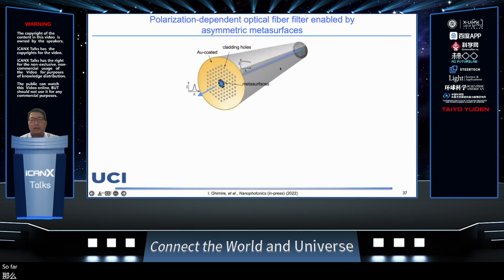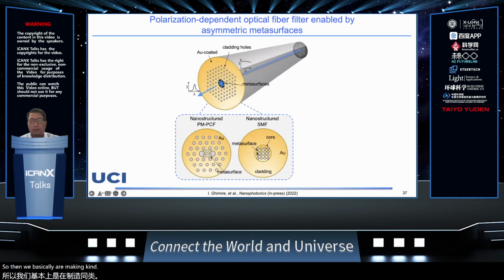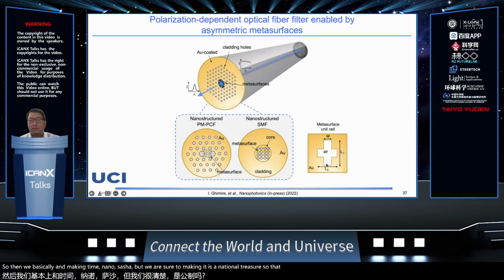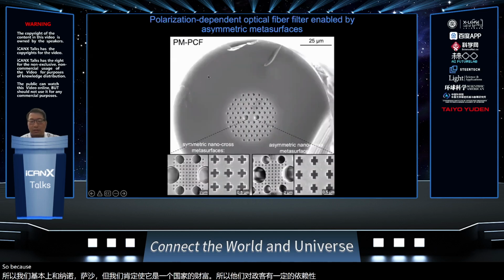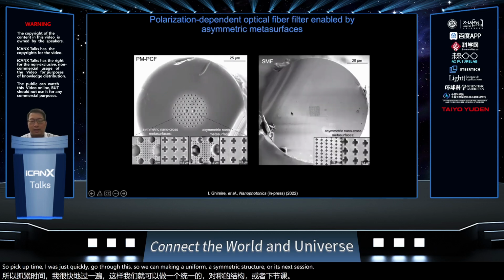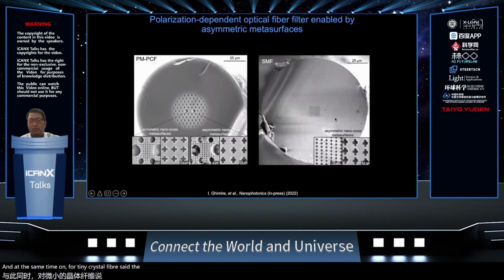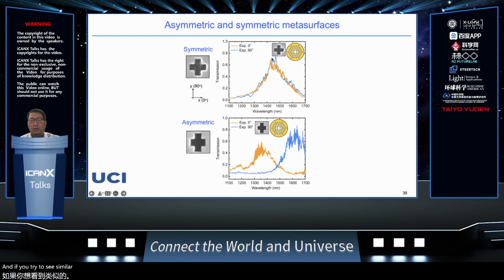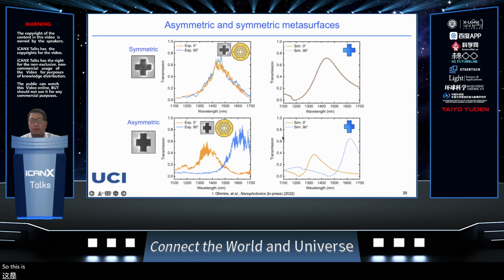So this is so far making lenses, and actually we can also make a filter on a fiber. We basically make tiny nanostructures, but we can also make an asymmetric structure so that you can have some polarization dependency. Because of time, I will just quickly go through this. We can make a uniform symmetric structure or asymmetric structure, on photonic crystal fiber or standard optical fiber. If you look at the symmetric structure, for two polarization states you have a filter with the same wavelength range here. But if you have an asymmetric structure, you can make a polarization-dependent filter. Depending on the polarization, you can have a different color filter coming out from this optical fiber. This also matches quite well with the simulation.